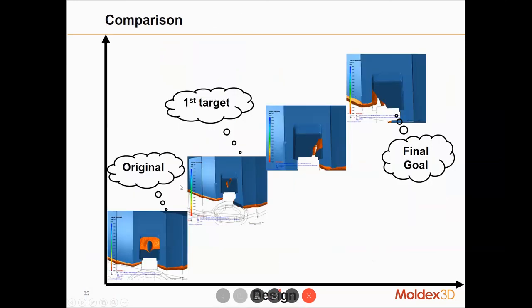So after the first modification, with a part thickness modification, they were already able to achieve their first target. If we look at the melt front, there is actually no air trap region on top, and the melt actually meets on the bottom right side, which means there will be no weld line on top and no air trap on the top appearance side. And after they change both the runner and the part design, this is the final result they get. And as you can see, there will be absolutely no air trap on this small geometry after the modification.